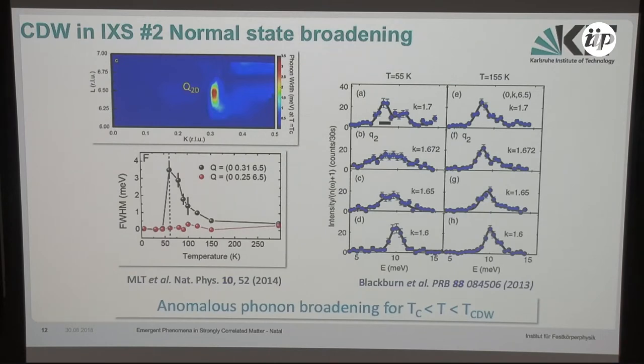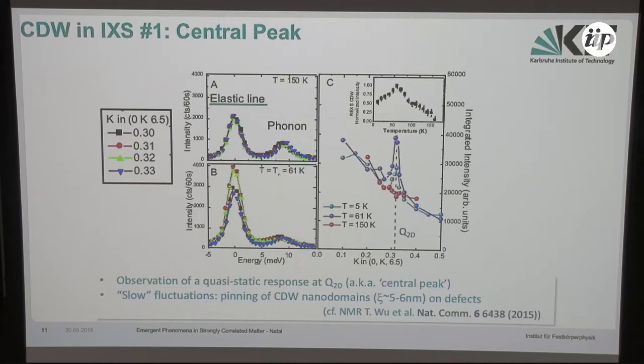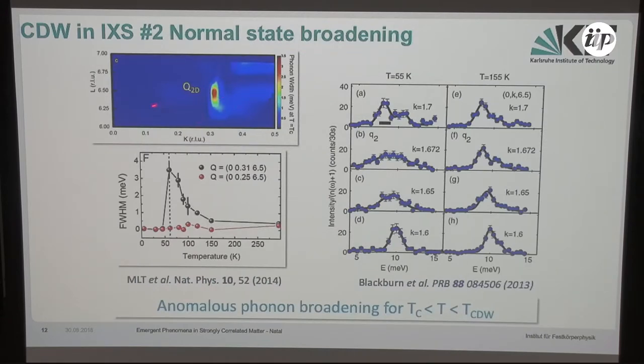The second interesting signature is when I look at the phonons in the normal state: they broaden, and that's very anomalous. This is a very big broadening. I have a phonon mode at low energy here, close to 8 millielectron volts. If I look at its linewidth, I find that it broadens by almost a factor of 2, even more actually, up to 4 meV linewidth, but just at the Q2D wave vector. And when I go into the superconducting state, this broadening completely disappears. So that's my second signature of the CDW in the X-ray spectrum.